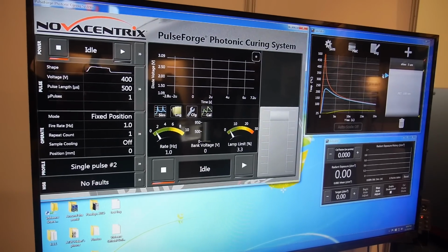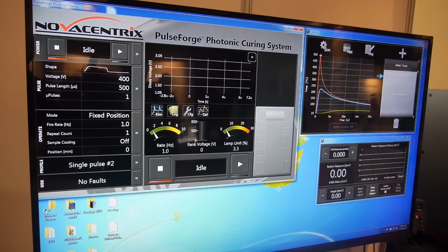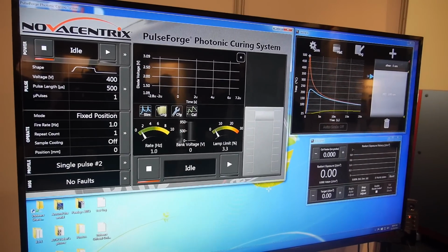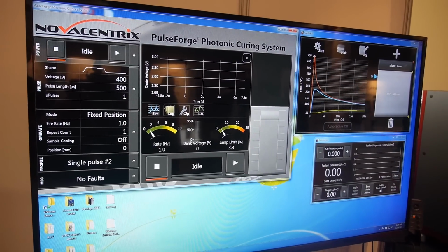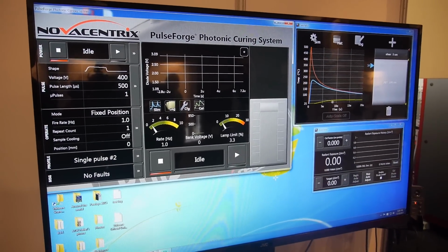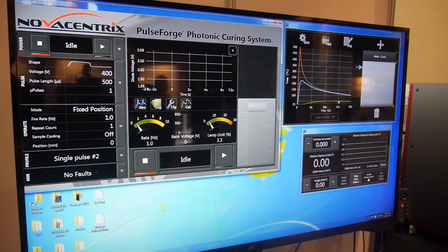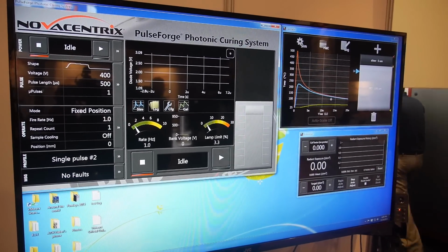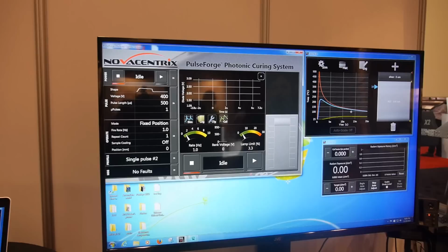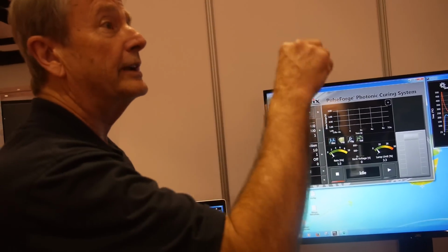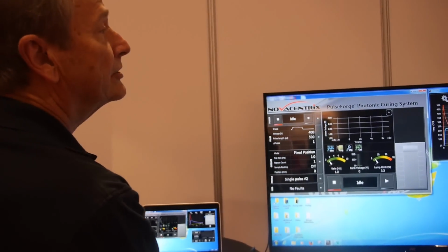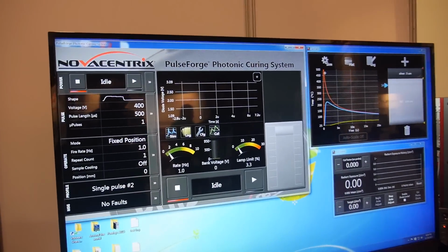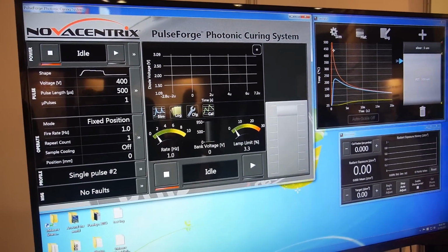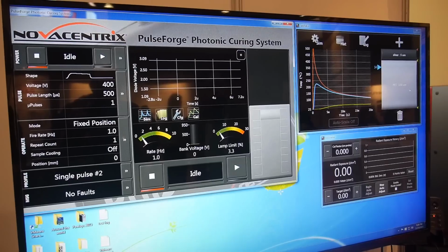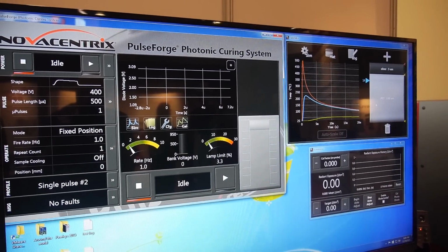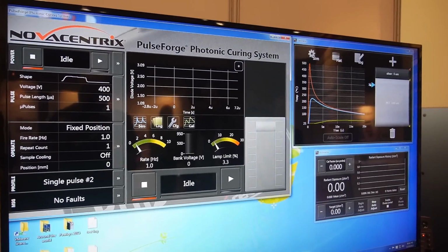If you look here, you can see that the top surface with these pulse conditions reaches 500 degrees C. The bottom surface barely gets heated. And that's one of the real secrets of PulseForge, that we can create a thermal gradient from top to bottom that allows us to take a material that might require going to 500 degrees, coated on a temperature-sensitive substrate, and most of this temperature-sensitive substrate never gets heated.